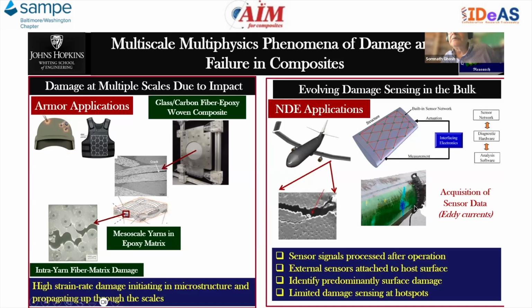Now, typically, different NDE techniques have been used. For example, this shows a built-in sensor network involving actuation and measurement. This consists of a sensor network together with diagnostic hardware and analysis software. And this other one corresponds to sensor data acquired through eddy currents. Typically these sensor signals are processed in a posteriori fashion, that means after the operation. External sensors are typically attached to the host surface and identify predominantly surface damage, and therefore we have limited damage sensing at the hotspots, which could be deep down in the microstructure somewhere.